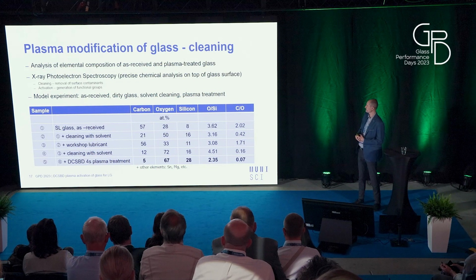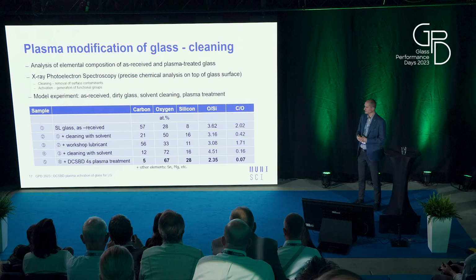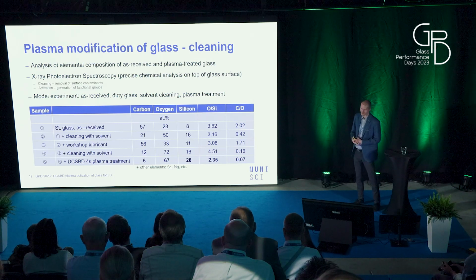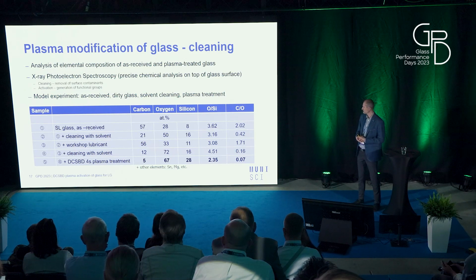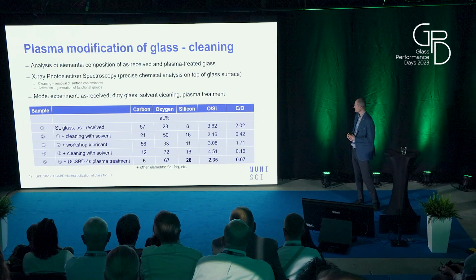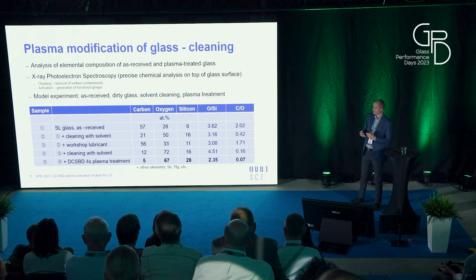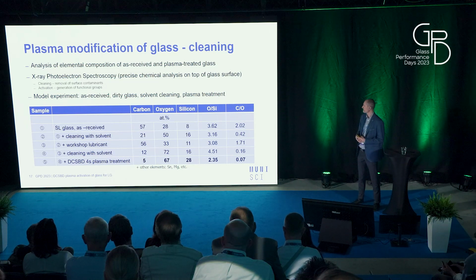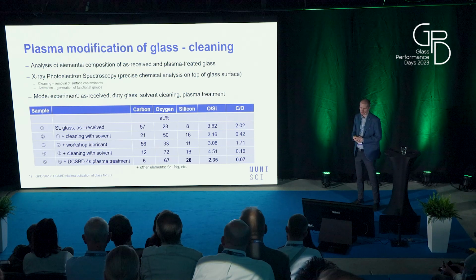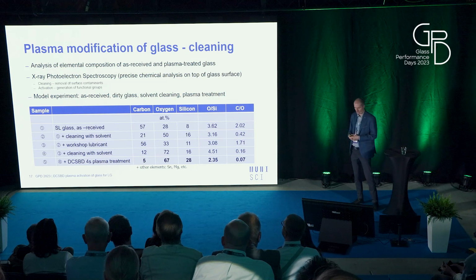We can calculate, for example, the oxygen to silicon ratio, which represents the cleanness of the glass. We can see a rapid decrease from about 3.6 to about 2.3, 2.4, which is very close to 2, which should be for clean glass. The carbon to oxygen ratio represents the contamination, and we can see that there is a sharp decrease from more than 2 to less than 0.07.